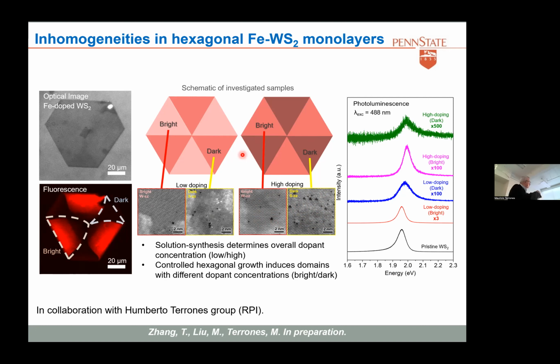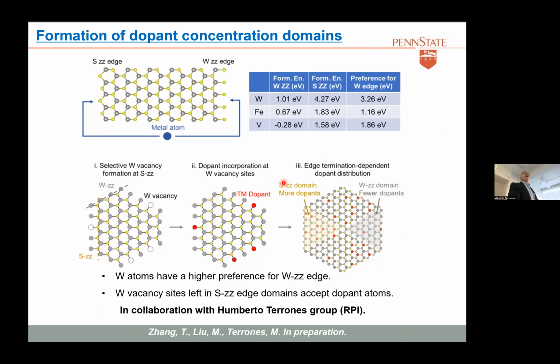The hexagonal alignments, the interesting thing is the termination of the edges. So when you do the edge termination, these are zigzag edges. So if one edge is metal terminated, the other edge will be sulfur terminated. So it's metal, sulfur, metal, sulfur, metal, sulfur. So one thing that we found with theory was that the tungsten atoms prefer to go to the metal terminated edge. And the sulfur terminated edge tends to create metal vacancies. So there's more like metal vacancies. So the metal vacancies are more likely to be created in the sulfur terminated edges. So that means when you have these metal vacancies, that's very suitable for putting the other dopants. So what happens during growth is that preferentially the dopants go to these sulfur terminated edges, and this alternates every other phase. And that's our explanation for the finding.